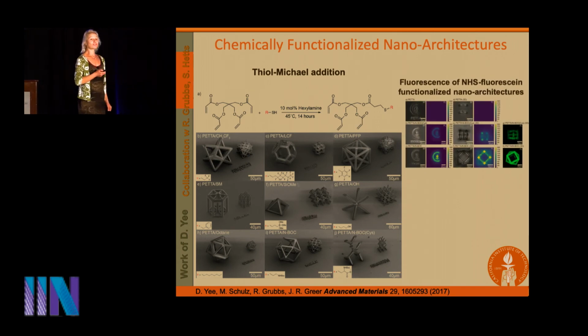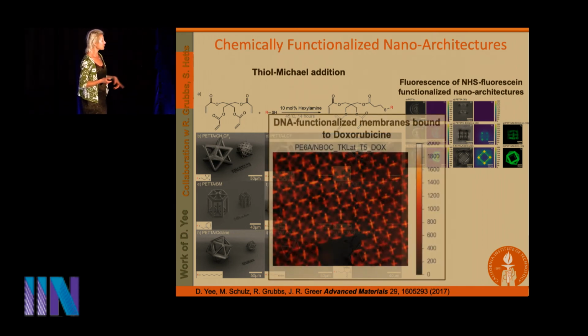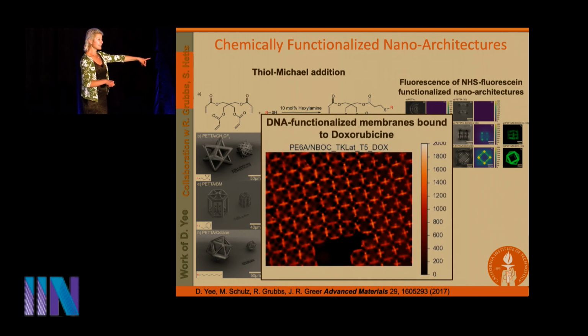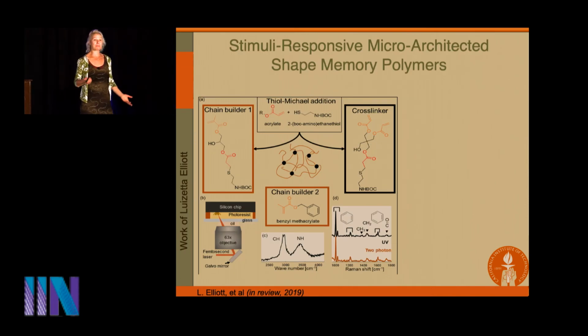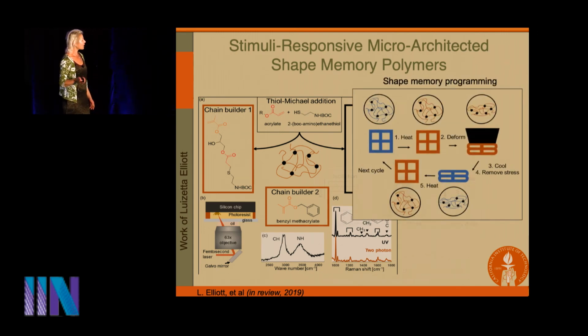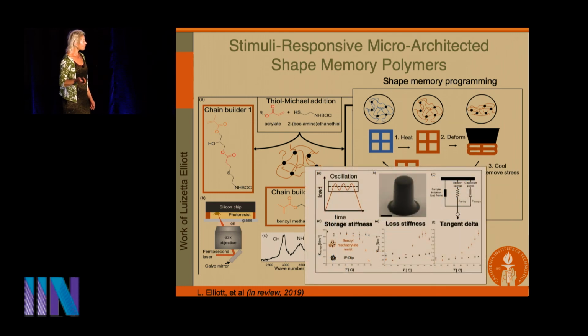So we also work with Nobel laureates at Caltech quite a bit. So this was our paper with Bob Grubbs, the first paper with Bob Grubbs that shows that you can also functionalize the surfaces of these structures, for example, with DNA, and then DNA can bind onto various chemotherapy agents, for example, like doxorubicin, so you can capture various chemical functionalities and make membranes out of them. Very recently, we started playing with shape memory polymers, so you could start building different chains and program your structures using the glass transition method, for example.